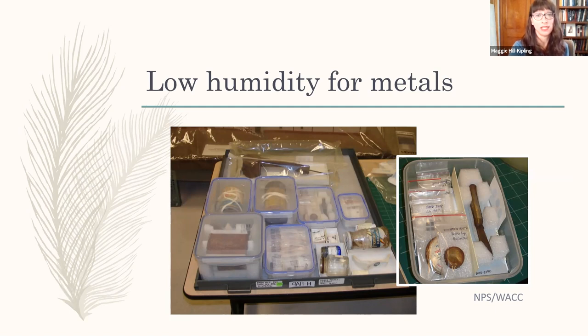These are storage containers that have been made using plastic gasketed boxes like you would use for food storage. These are polyethylene boxes. They're much thicker than other polyethylenes. So even though polyethylene isn't always a very good vapor barrier, the increased thickness in testing showed that it was able to slow that buildup of humidity within the boxes. And then you've got silica gel placed in here as well. In the back of this drawer, you can also see another object that is using Escal, and these actually even tend to hold up better over time.